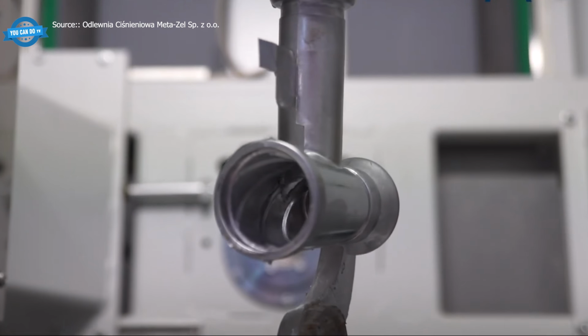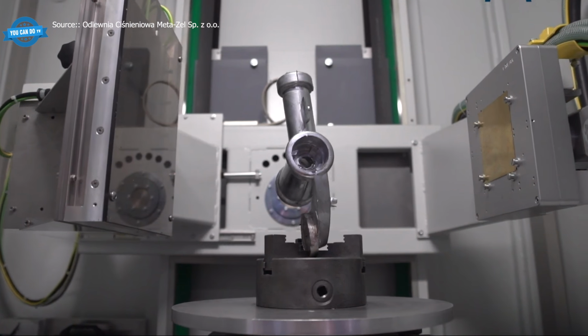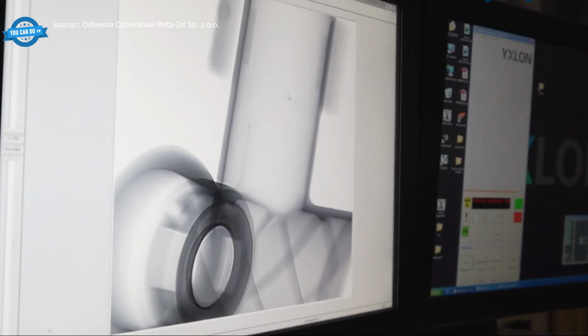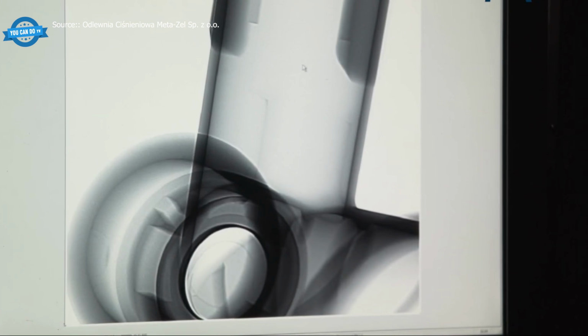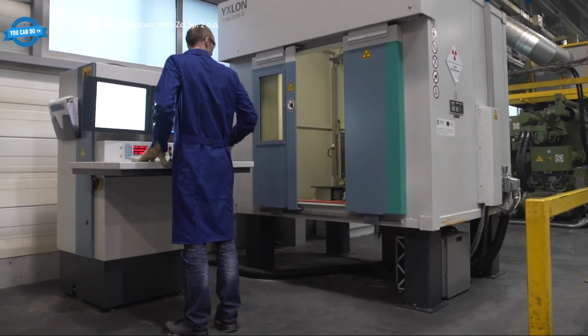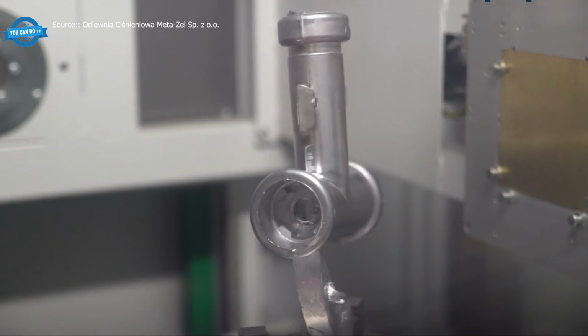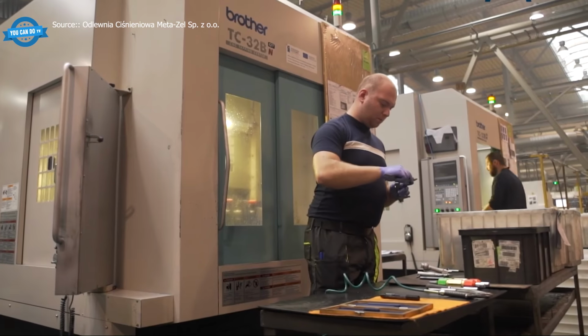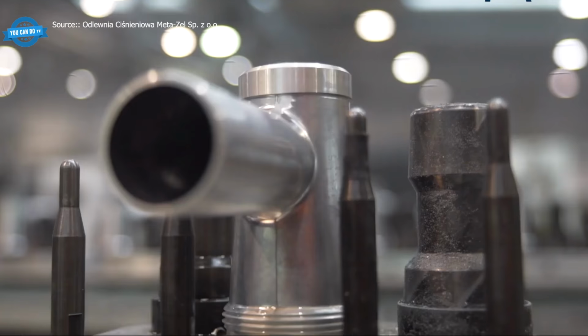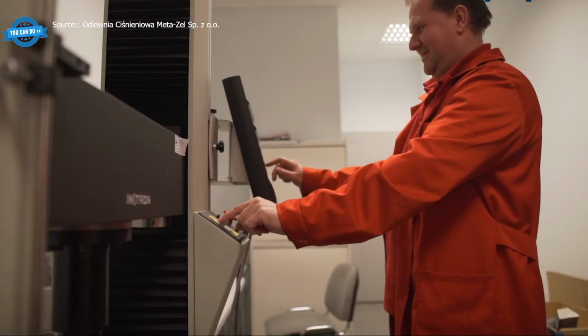Once injected and pressed, the aluminum solidifies in seconds. X-ray inspection then checks whether the inside of the part matches the outside, because a cast part that looks perfect can hide voids nobody would find until the customer starts calling. Machining, trimming, and precision measurement follow, with tolerances checked down to 3 microns.